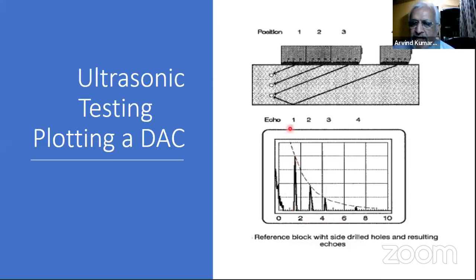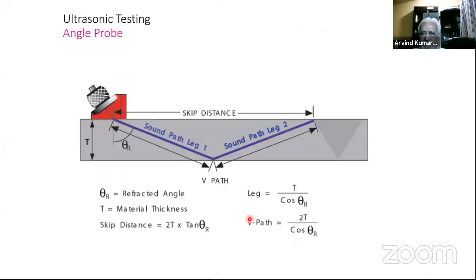Okay. So once I have this DAC, I will set a range and do scanning on the weld. I'll show that in the subsequent slides. You scan between the peaks. If you find a peak in between, you know what percentage of this height I'm getting a peak at, so we have to evaluate. And if it crosses this peak, I know that my defect is bigger than what I have calibrated for, and definitely more than 2 millimeter size or something like that. That is why you need a distance amplitude correction curve for weld scanning.